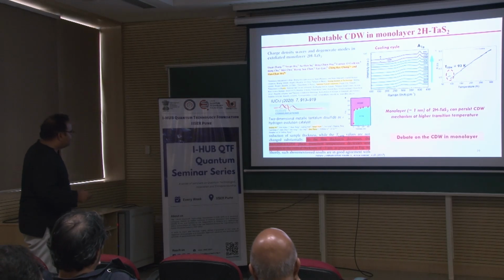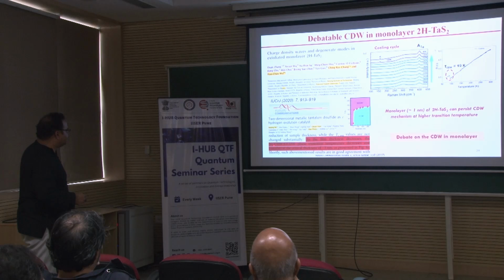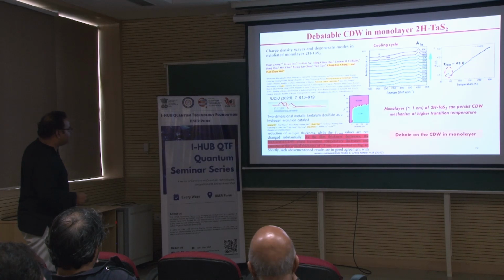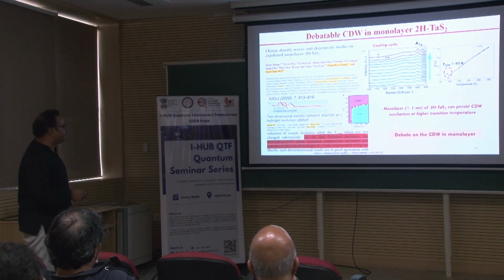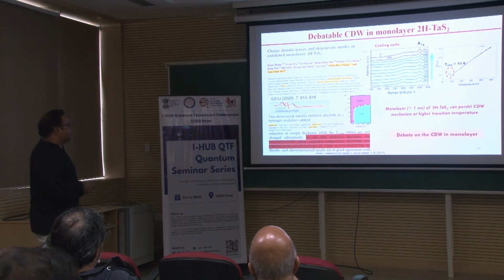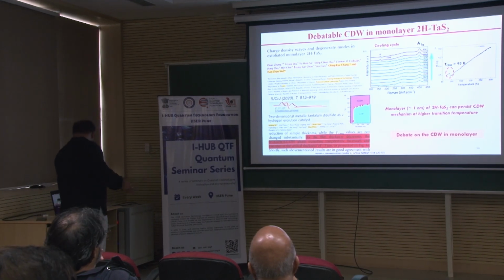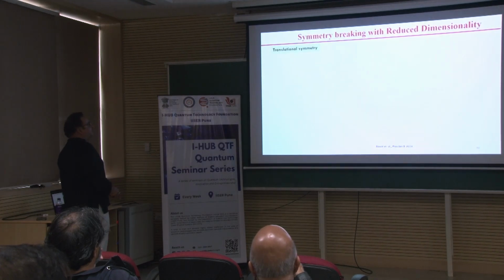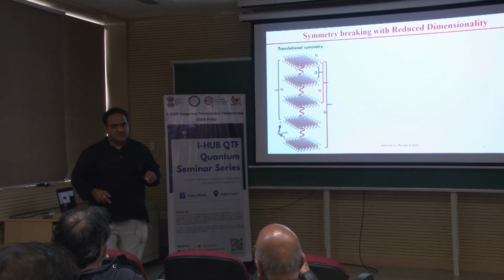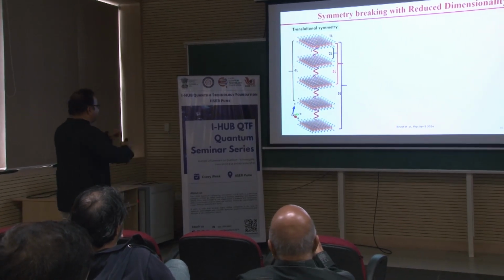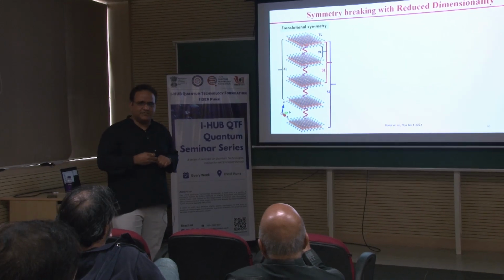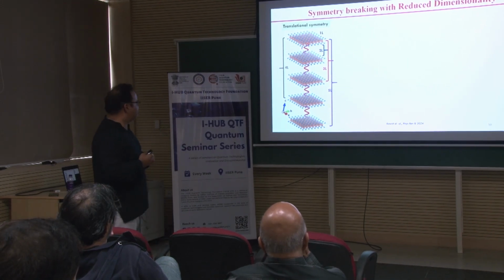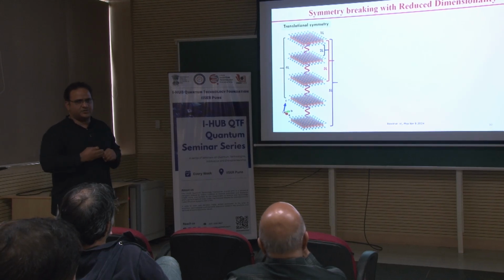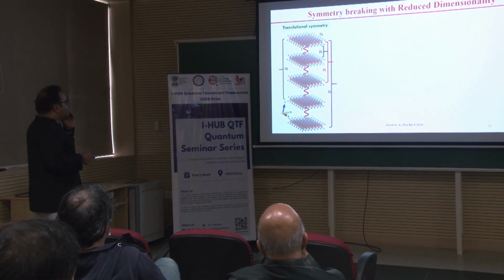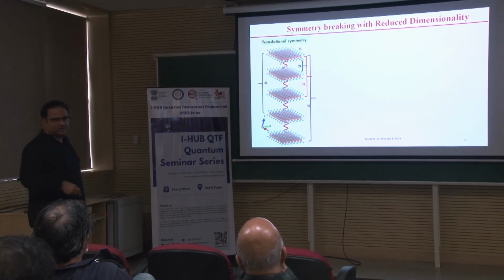Now this paper says as the film thickness decreases, the commensurate charge density wave phase transition temperature decreases and vanishes at the critical thickness of 3 nanometer, as presented in figure 4e or something, okay, all right. And we try to see that. So there is a debate actually in monolayer whether the charge density wave is there or not. Somebody has done measurements with TEM on the monolayer, but it is not clear. Mostly non-linear optical measurements also people have tried, yeah. So now I am talking about when I am going from bulk to monolayer, what exactly is happening.